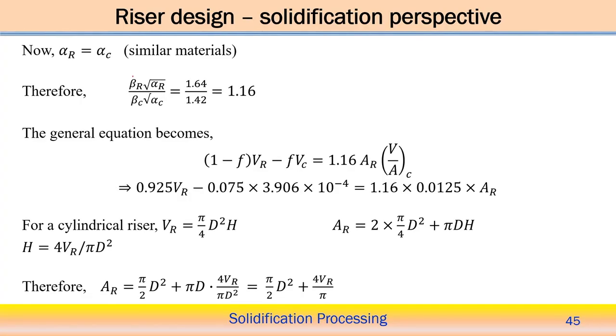So, both the liquid metal as well as the mold material are the same for the runner and riser. Therefore, thermal diffusivity will be the same in this case. So, alpha r equals alpha c for the similar material. Now this terminology, beta r, square root of alpha r, by beta c, square root of alpha c, equals the ratio of beta r by beta c. So, 1.16 we can calculate.